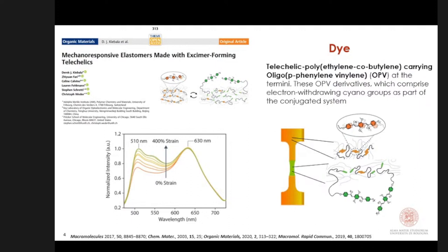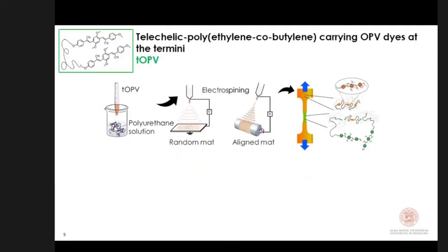So what's the novelty of our work? Because we use the same telechelic dye, the same polymeric matrix, which is a polyurethane matrix, but we now change the processing of the material. We use the technique of electrospinning.